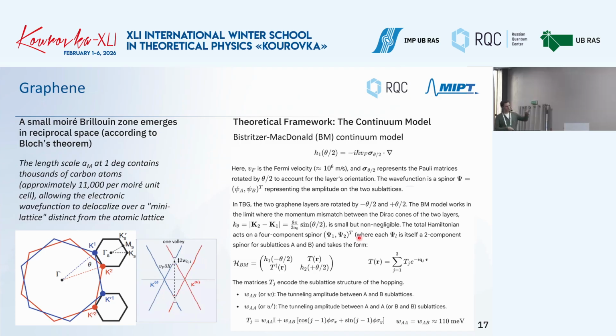There are, first of all, the Hamiltonians of the single monolayers 1 and 2, and then there are the matrices that encode the sublattice structure of the hopping. This parameter, which I tried to display here, is the tunneling amplitude between A and B sublattices, and the tunneling amplitude between A and A. As I mentioned, there are slightly different values, like 80 millielectron volts and 110 between them. This is important because it is energetically not the very same.